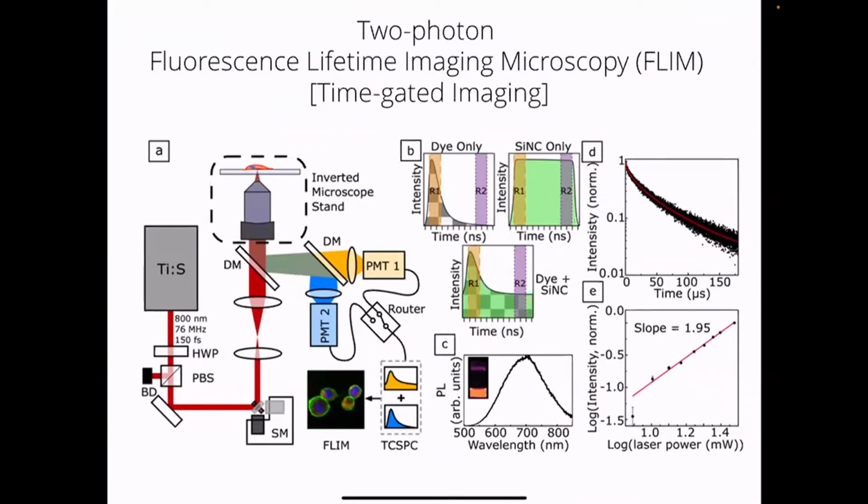In addition to that, we can do multispectral imaging using the long photoluminescence lifetimes of the silicon. Silicon as a semiconductor has an indirect band gap, so it really doesn't emit light as a bulk crystal. When you make nanocrystals, you change the selection rules a bit, and radiative electron hole recombination begins to become allowed, but it's still an indirect band gap, and so the lifetime is relatively long.